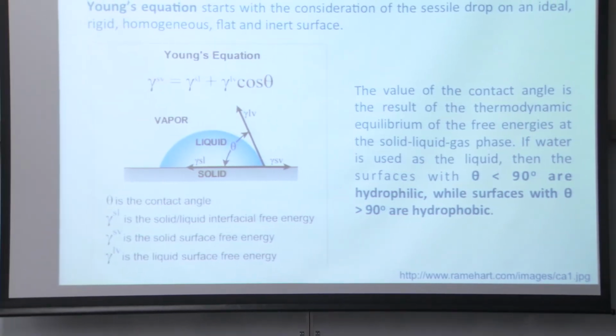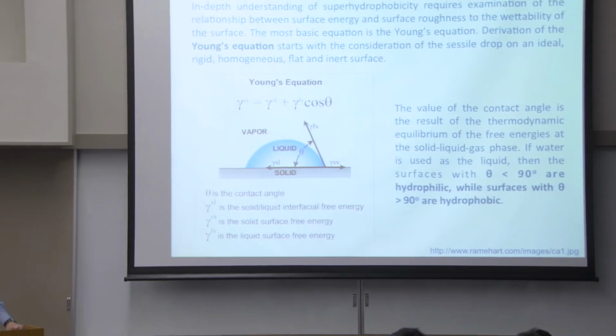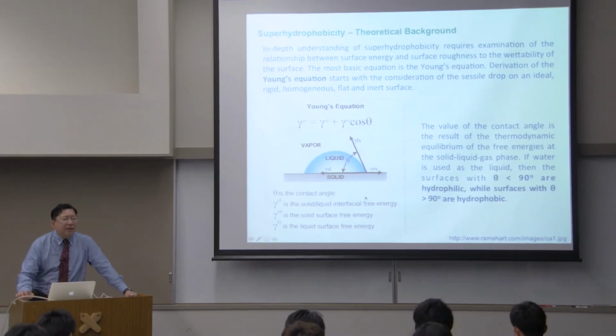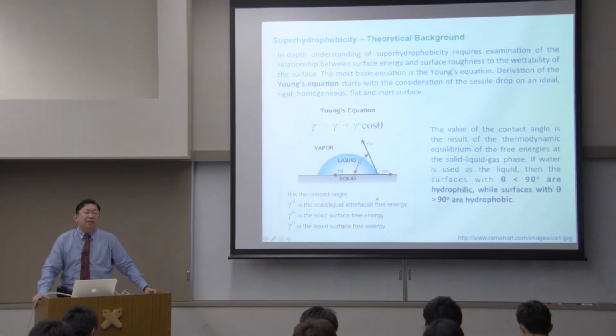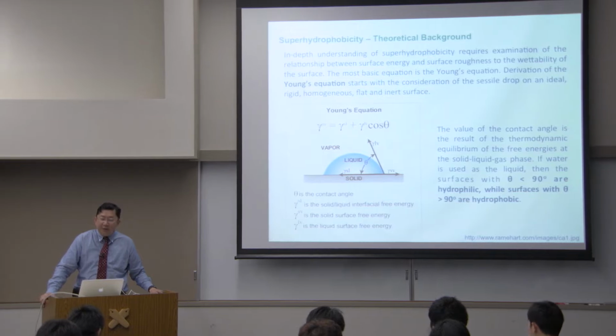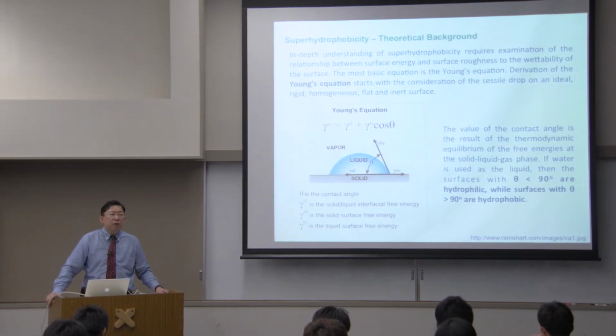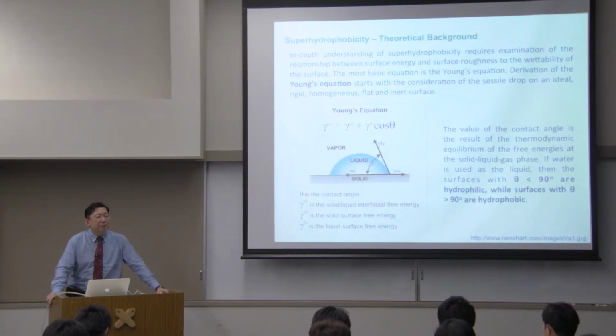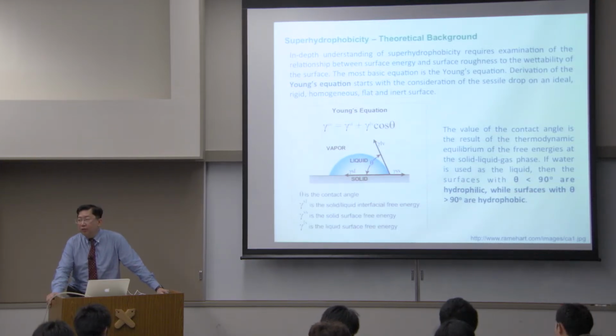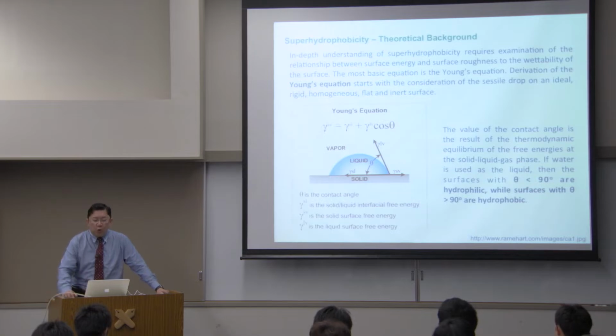So the Young's equation has many assumptions. One assumption, of course, is that you have a solid plane, independent or in the absence of roughness, giving you pure surface energy calculation without the correction for the effect of roughness or trapped air.